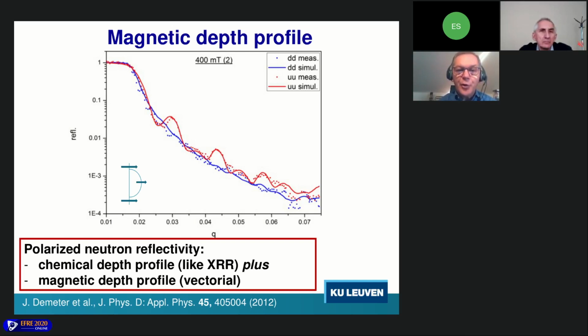And the fittings that I show here are in fact simply made with a model where the magnetization is largest at the top and the bottom of the film, but smaller in the middle of the film because some of the cobalt has been transformed into cobalt oxide. And you see that we actually can get a good fit with such a model where you have a sort of distribution of the magnetization as a function of the thickness.